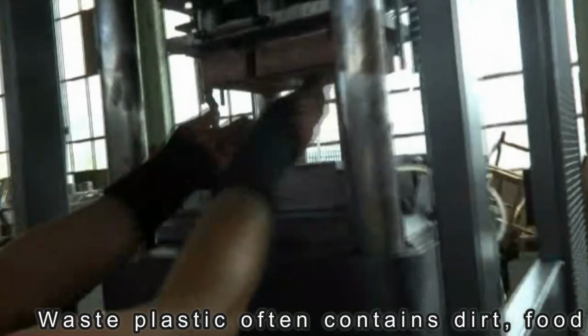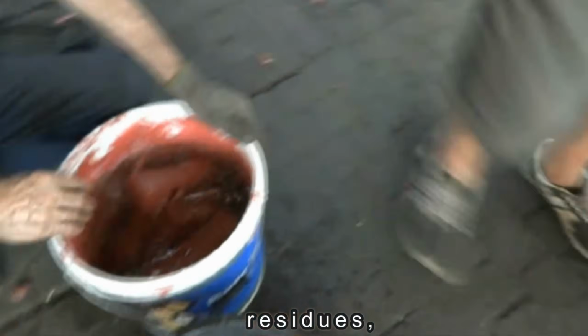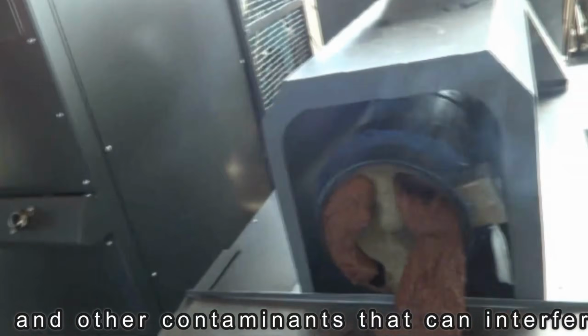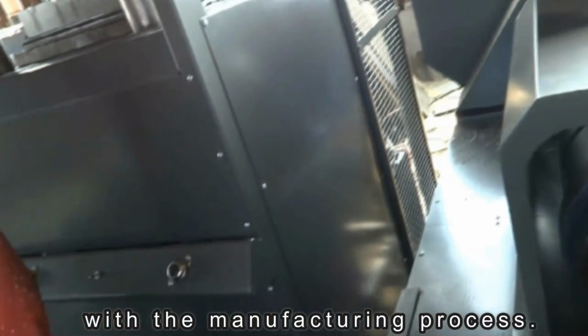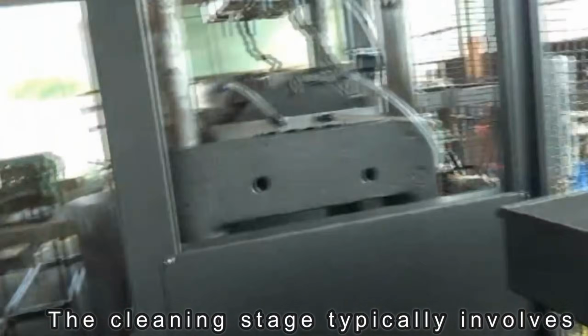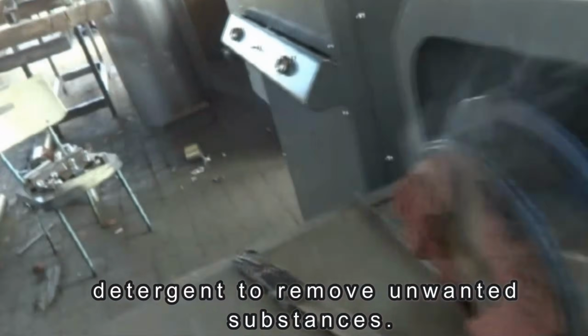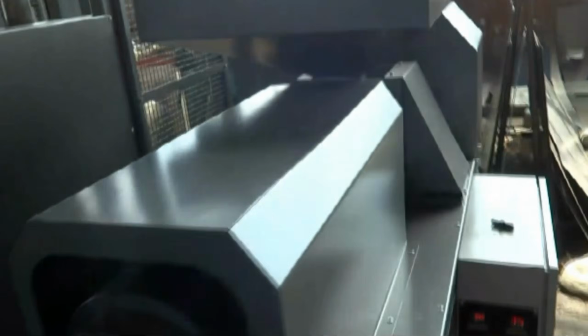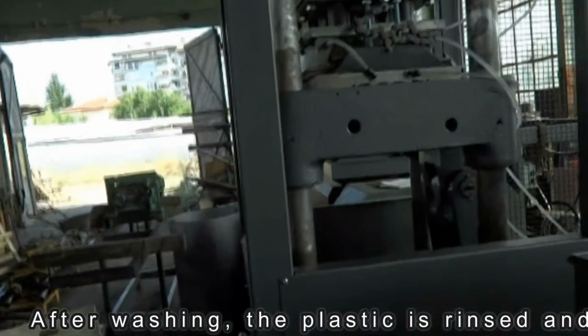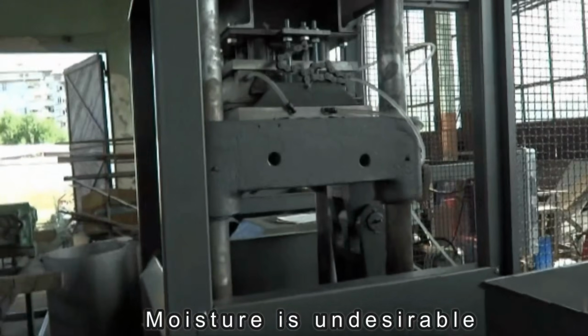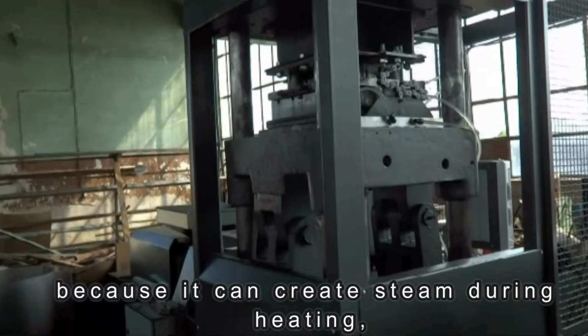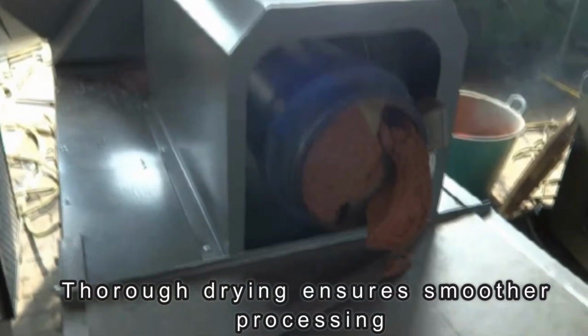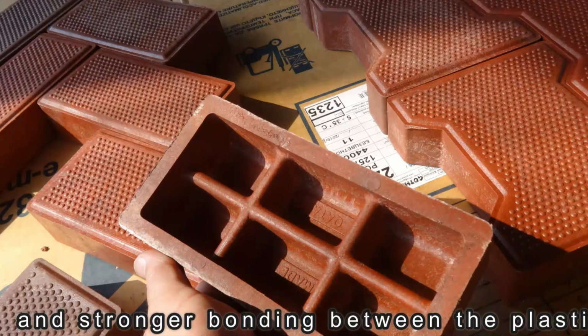After sorting, the plastic must be cleaned thoroughly. Waste plastic often contains dirt, food residues, oils, adhesives, and other contaminants that can interfere with the manufacturing process. The cleaning stage typically involves washing the plastic with water and detergent to remove unwanted substances. After washing, the plastic is rinsed and allowed to dry completely. Moisture is undesirable because it can create steam during heating, leading to bubbles, voids, and defects in the finished product. Thorough drying ensures smoother processing and stronger bonding between the plastic and sand.